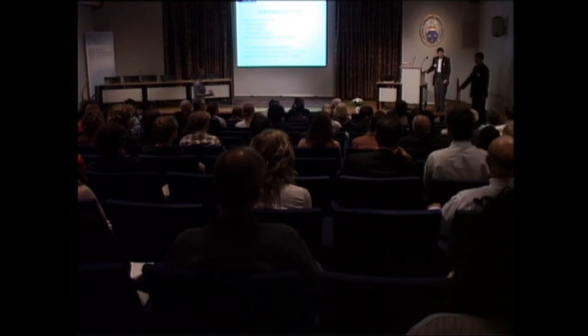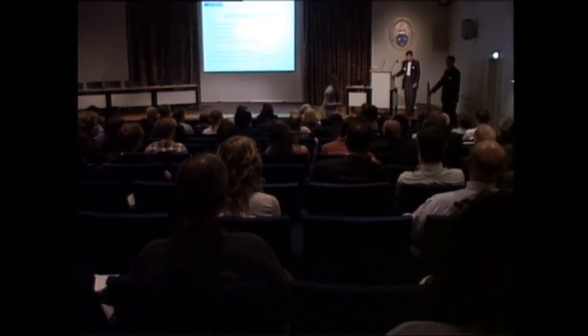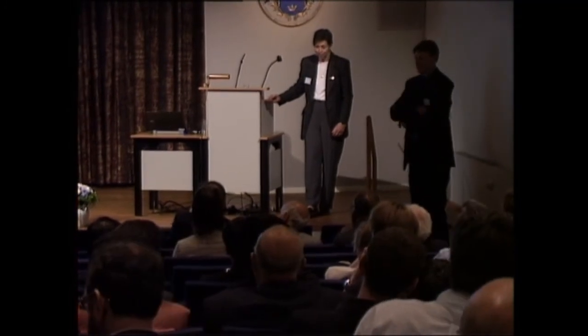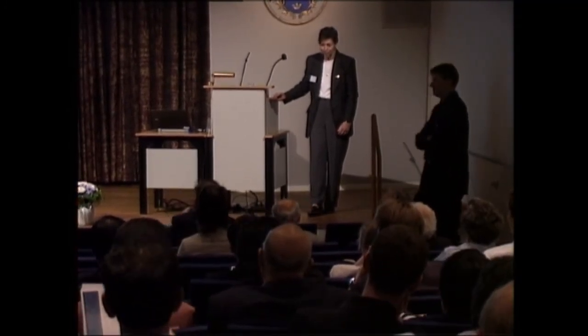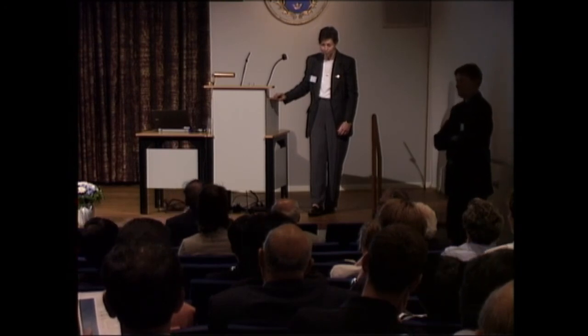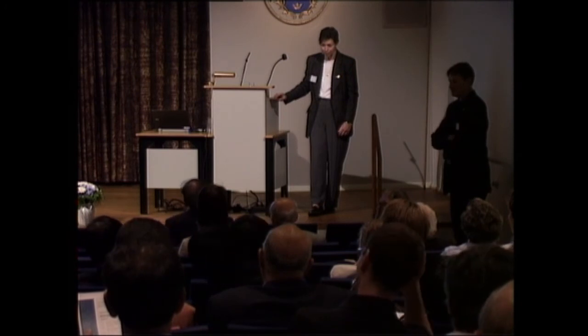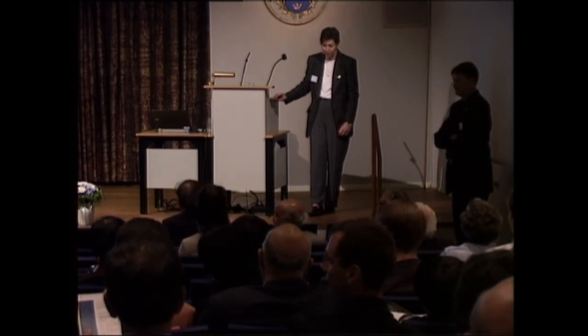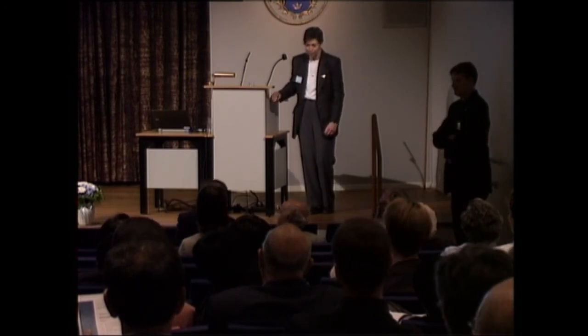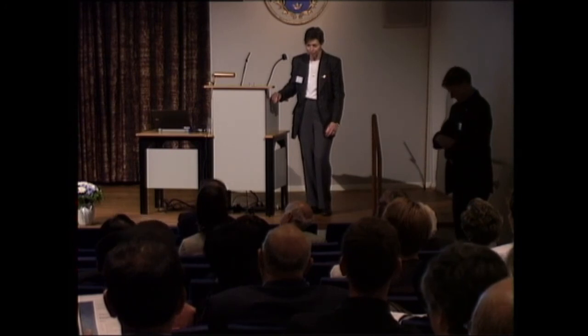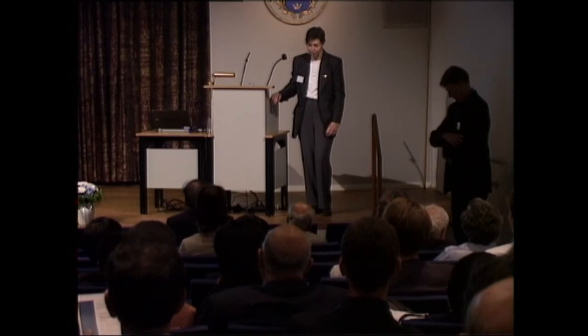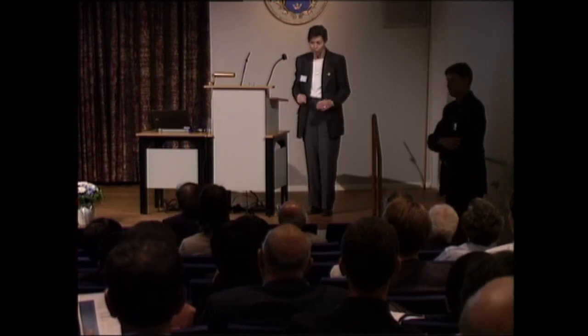One of the very pretty things that comes out of your lecture is you sort of juxtapose the hard matter synthesis and the soft matter. So we look at the elegance of putting these dendrimers together. And I think the other thing it illustrates is how primitive our ability is to make a really well-defined, as we like, nanoparticle or nanoparticle assembly, or there are lots of different kinds of titanium dioxide, as you know. And there's a current feeling that sometimes it's even the interface between phases or a disordered phase immersed in an ordered phase that is most catalytically important. That's why we found the core-shell clusters to be so important, because we would have the ability to try to characterize that interface between the metal and semiconductor or two semiconductors. Right. Very important point, Tobin.